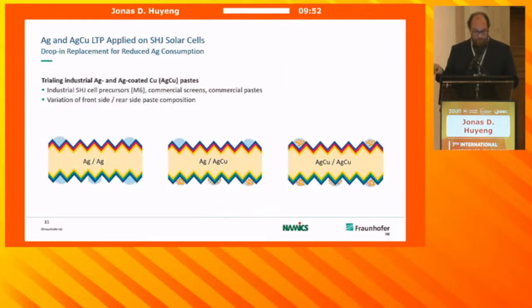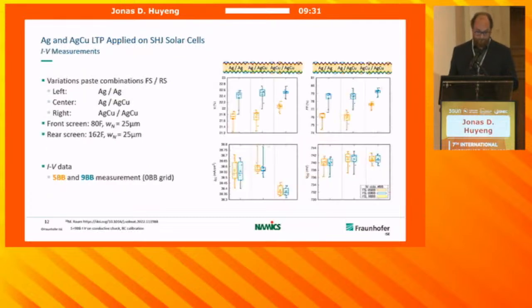And then I want to move on to showing some results on cell level. So here is an example where we've used an industrial solar cell precursor on M6 format, commercial screens, commercial paste, and we did this variation of the reference metallization with silver on front and rear side, only replacing the rear side silver with silver copper, or replacing both sides with silver copper. And you can see it in the same order from left to right: silver, silver, silver, silver copper, silver copper, silver copper. And we had 0 busbar grid.